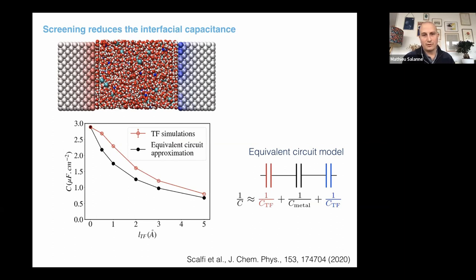But if you apply this approximation, you see that you will neglect some effects, and you will quite importantly get too low a capacitance, and this is due to the interplay between the liquid and the charge. And of course, when you allow more screening, your liquid will not respond in the same way as in the metal, and so you cannot expect that all the effects are decoupled.